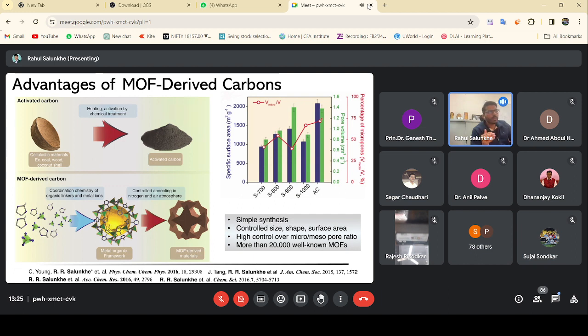Although we have this kind of commercial activated carbon, still people are trying to develop different kinds of carbon materials, and one of these types of carbon is called MOF derived carbon. MOF stands for metal organic framework. So a metal organic framework is very simple in synthesis. As we can see, these are the metal precursors and these are the linkers, maybe 2-methylimidazole in this case. We just disperse these linkers with the metal ions, and they form a link, and because of that coordination they form a metal organic framework.